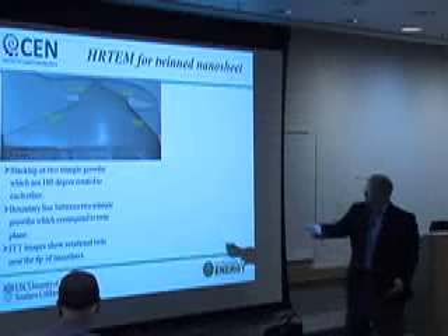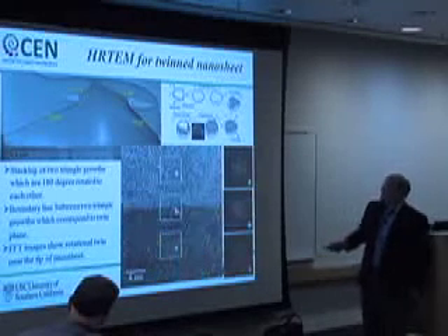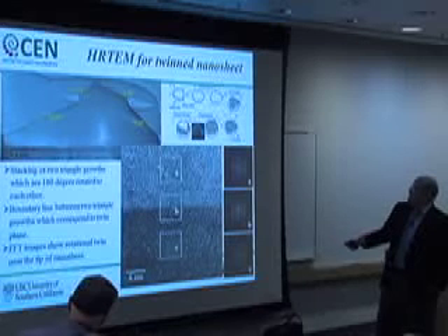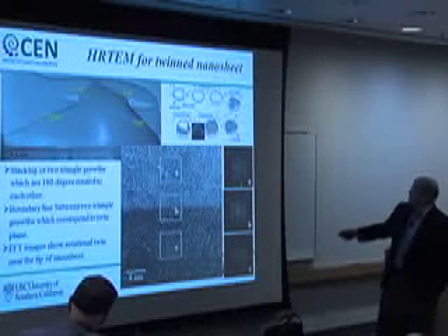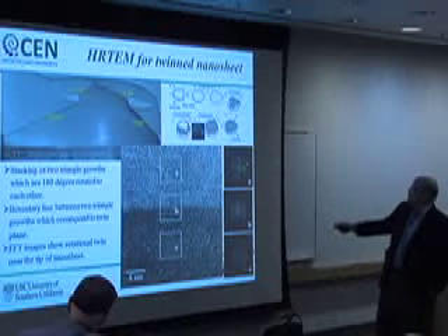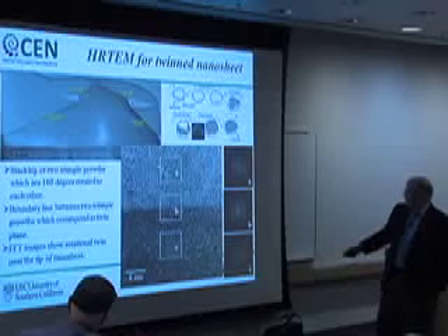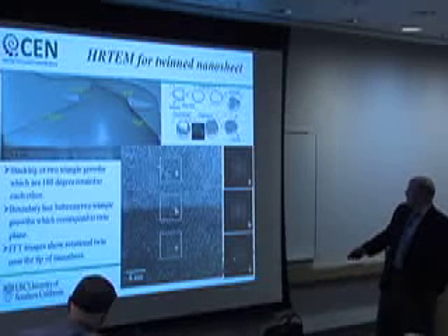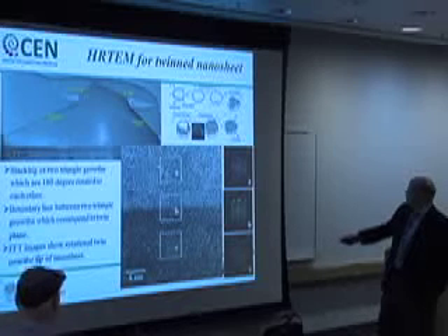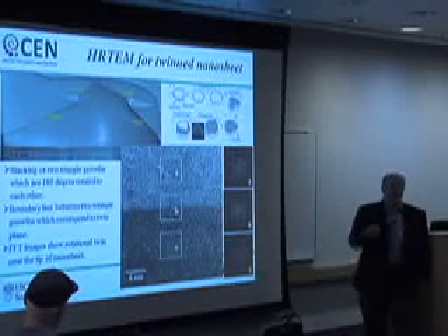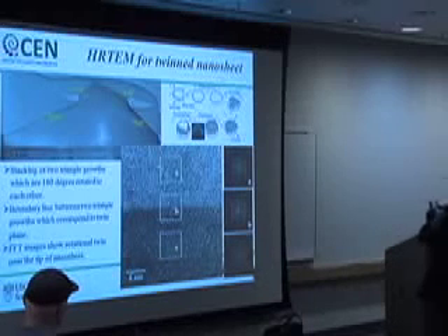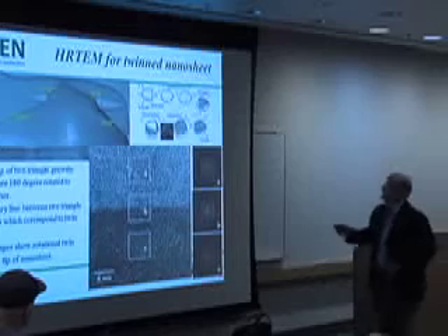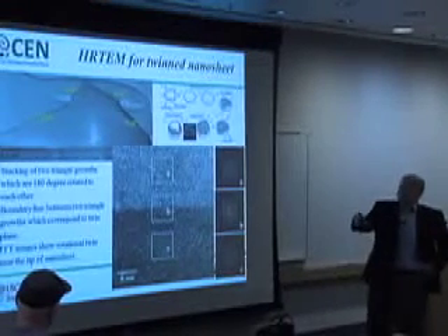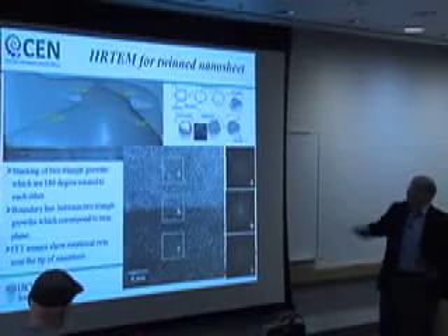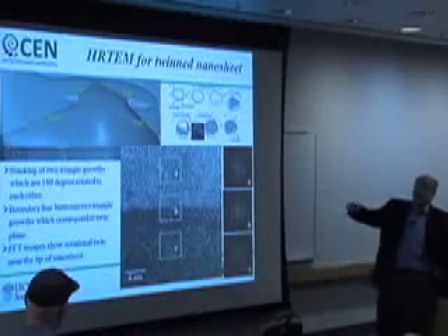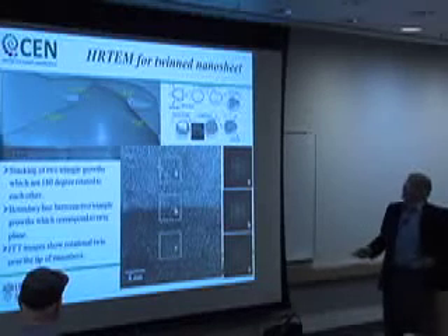So we looked at TEM of that, and sure enough, if you look at the Fourier transform of the diffraction over here, you get the expected pattern. The pattern over here is shifted slightly, and if you look at the region in between, you pick up the combination of the two, indicating that there's really just one twin boundary formed at that interface. And so, anyway, that sort of lends credence to this model of the nanowire growth and says that these are inherent properties of nanowires grown in this particular way.